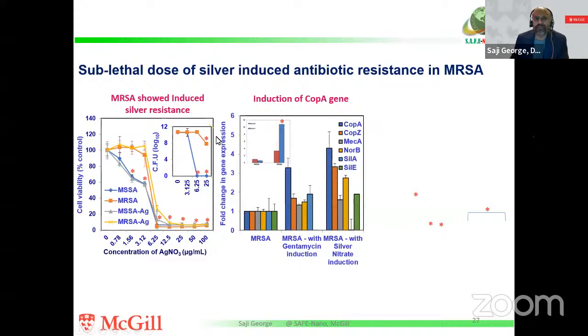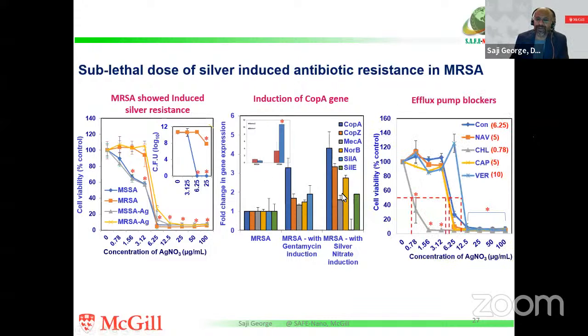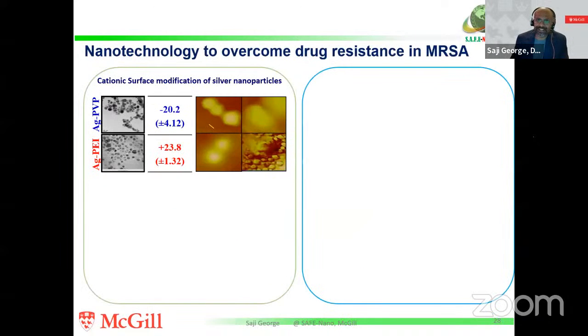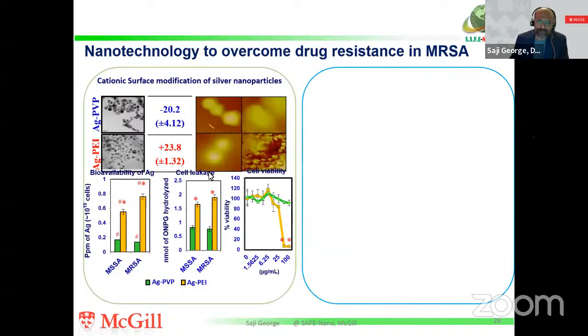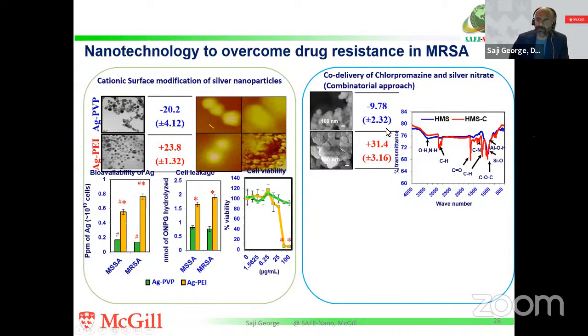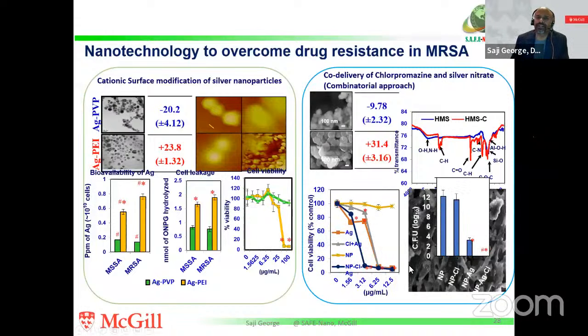Now, what we see is that bacteria like multi-drug resistant Staphylococcus or methicillin-resistant Staphylococcus, for example, also resist silver because of the same function of efflux pumps. And we found that there is an activation of those efflux pumps when you prime the bacterial cells with a smaller concentration of silver. We also looked into molecules that can inhibit the function of efflux, and we found that there are such molecules. Based on that knowledge, we redesigned the silver nanoparticle, which can go and bind with the bacteria. What we see is the bacterial cell nicely decorated with our silver nanoparticle, in comparison to a silver nanoparticle which is negatively charged, and so it enhances the bacterial killing. Another possibility is co-delivery of these efflux pump inhibitors with the silver, which also improves the antibacterial property.